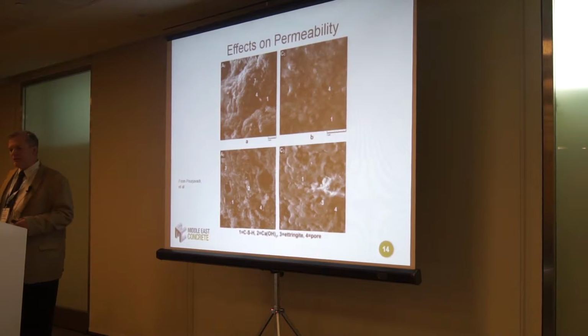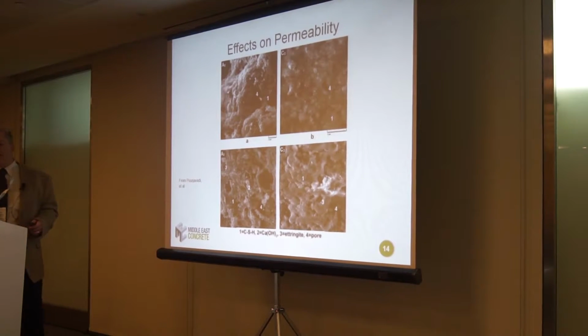These photographs are some of the best demonstrations of the closing of capillary voids that I could find. And you can see, hopefully, at least this number 4 here is pore space, and you can see how much it shrunk over here after a colloidal nanosilica treatment. Number 1 is CSH. The area beside the number 1 is a giant hole, and it's basically closed here. In this photograph, you can see a giant pore space here, and it's gone. You can see the pore space here is not completely gone, but it is shrunk. This pore space is gone.